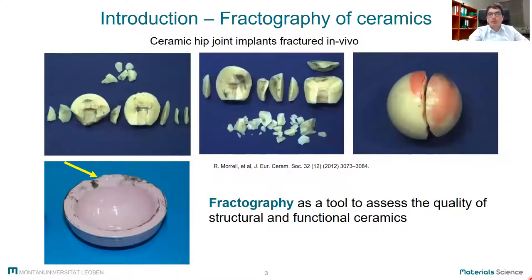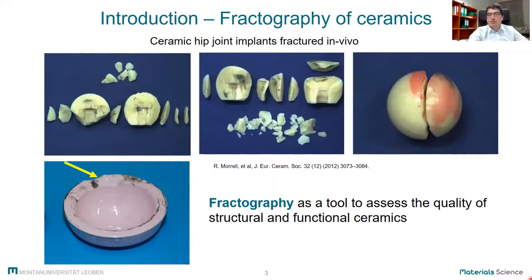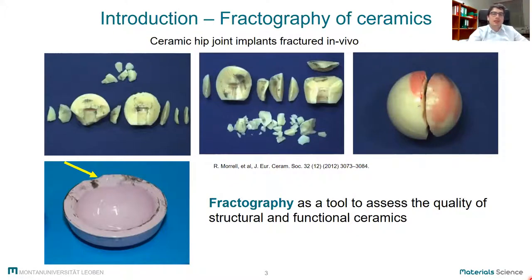In general, low resistance to crack propagation often causes spontaneous and catastrophic failure of ceramic parts and components. The brittle nature of ceramics can be associated with the immobility of dislocations during fracture. This brittle fracture in ceramic parts starts from small flaws either located at the surface or in the volume. Such defects can be generated during handling, in the production process, or also in service. Therefore, fractography can be used to assess the quality of structural and functional ceramics and to understand the origin and location of critical flaws.